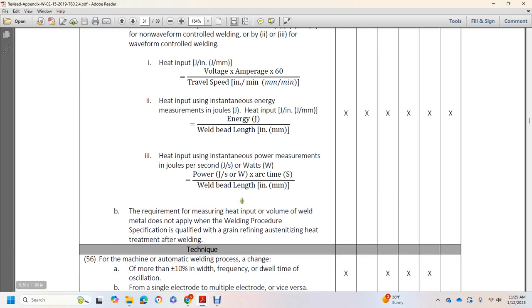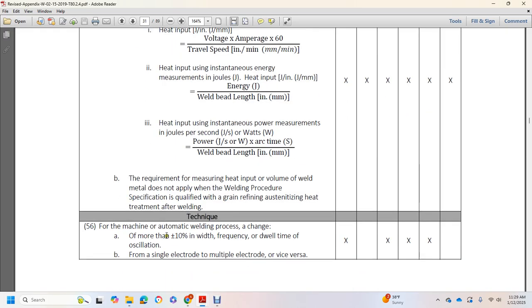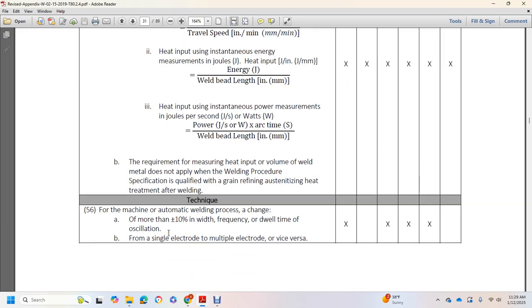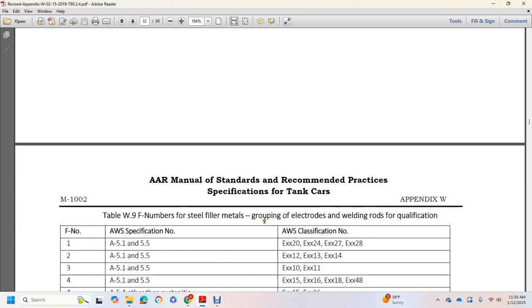The requirement for measuring the heat input with the volume of the weld metal does not apply with the welding procedure specification qualified with the grain refining austenitizing heat treatment after welding. Also, for the machine automatic welding process, a change of more than plus or minus 10% of the width, frequency, or dwell time of oscillation, or a change from a single electrode to multiple electrodes, or vice versa.